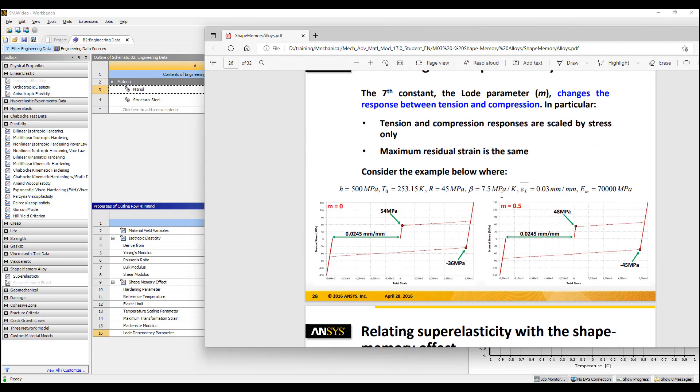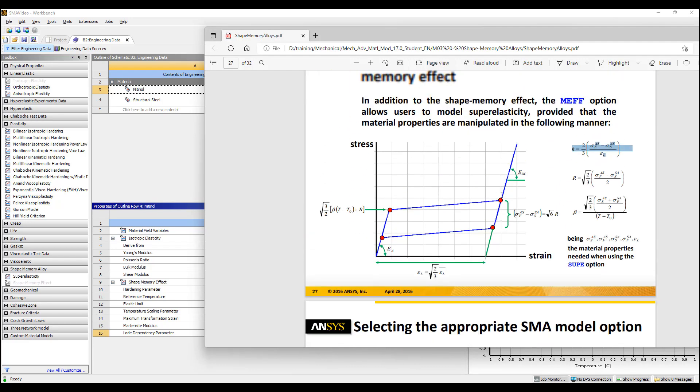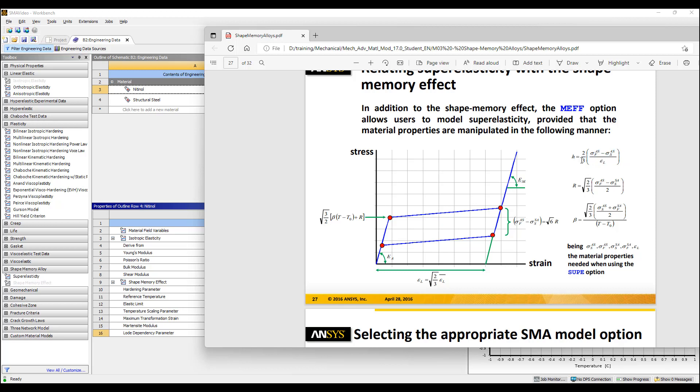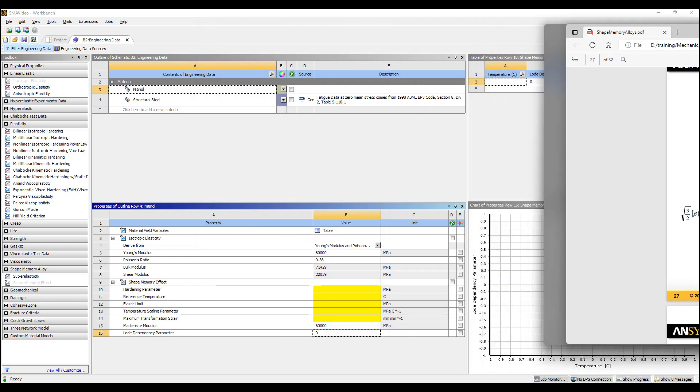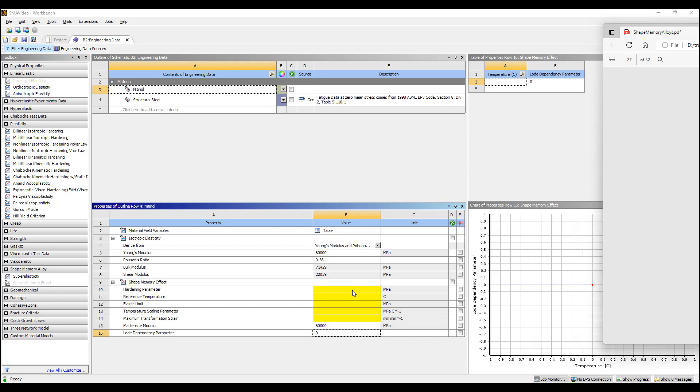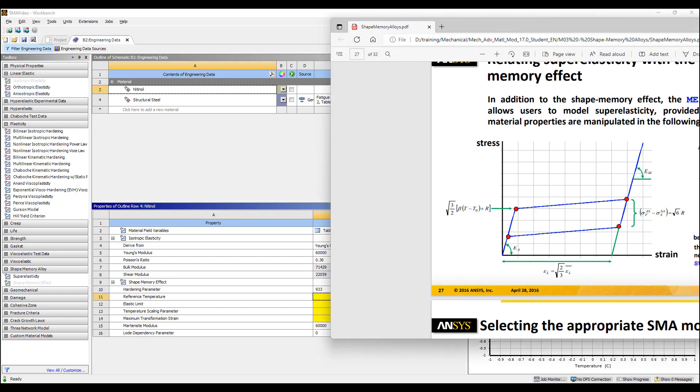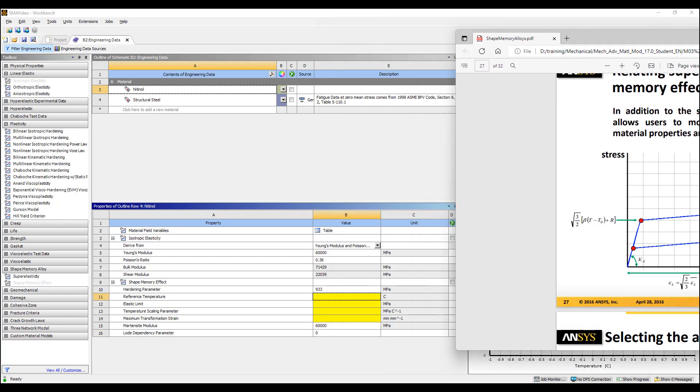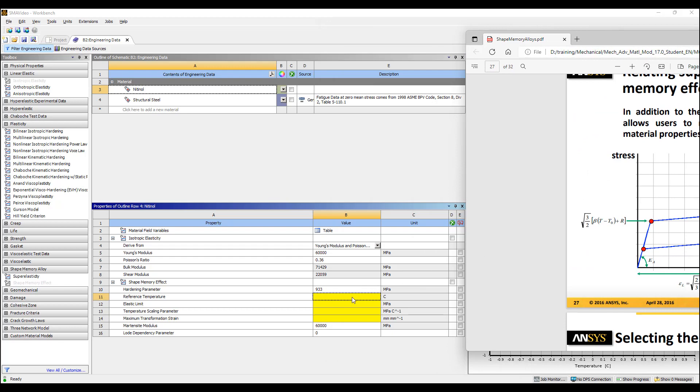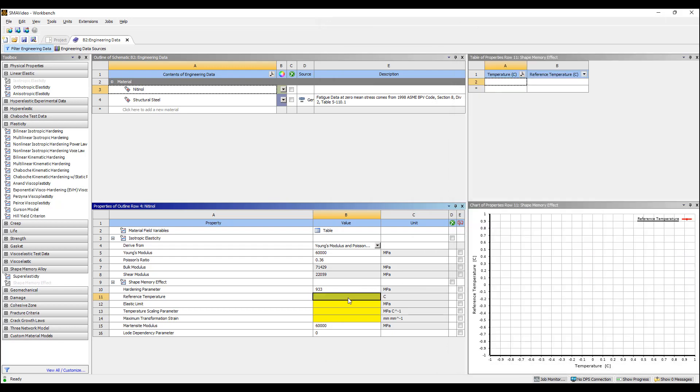The first value is H which is our hardening parameter. I've done the calculation, so this works out to something like 933 MPa. I'm going to set this to room temperature. We're not going to actually model the temperature effect, although we could certainly do that. Instead we're just going to run this as a super elastic type of material just to compare.